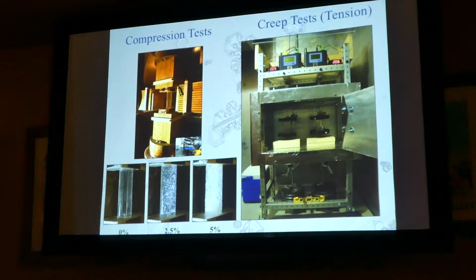So what we did was take the cylindrical pieces of ice and put them under compression and brought them to 5% strain. So we compressed them by 5% of what their original length was, and did that at different strain rates. So as fast as a minute, for 5% strain, and as long as like 13 or 14 hours to get to there. And this is showing what it looks like if you do it really fast, so like a minute or so. You get lots of cracks in the ice, but it doesn't just fall apart. It still has some structural rigidity to it.